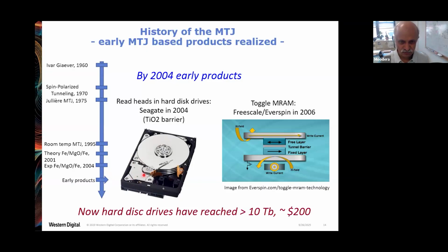And this is what the actual memory looks like. There's a disk here, which rotates anywhere from about 7,000 RPM to 15,000 RPM. And on top of that, you see there's an arm. At the tip of the arm is where the sensor is. That is where the magnetic tunnel junction is. So they were able to actually use the magnetic tunnel junction in this kind of structure.